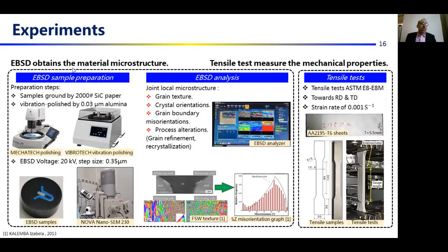For the experiment, EBSD obtained the material microstructures such as grain texture, crystal orientations, and grain boundary misorientation. Samples are polished and vibration polished prior to the EBSD test, and the EBSD test is conducted with a NOVA Nano SEM machine. Tensile tests also measure the tensile properties along the rolling and transverse directions to obtain the anisotropic material properties.